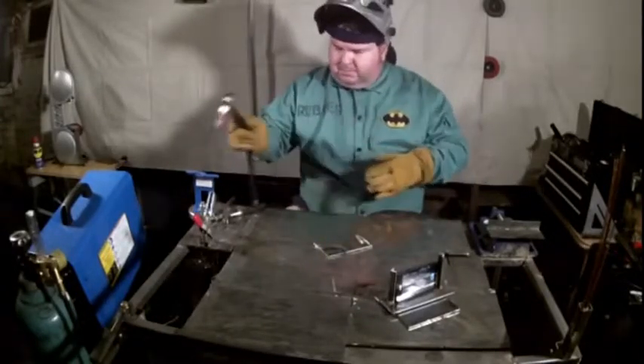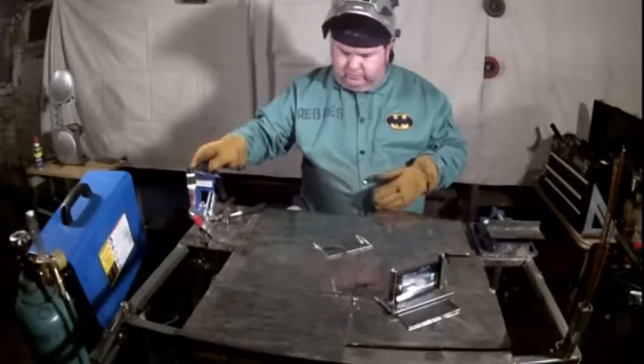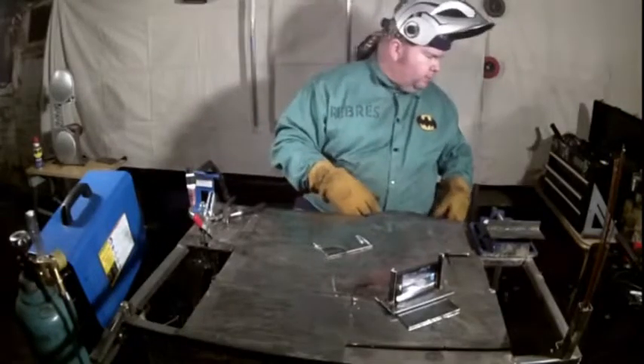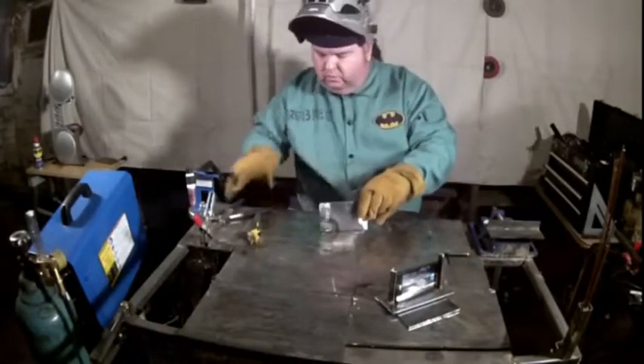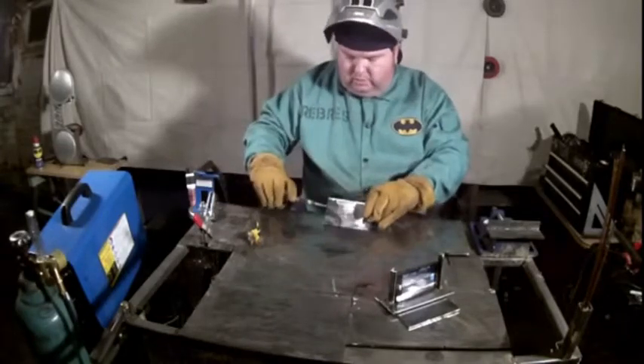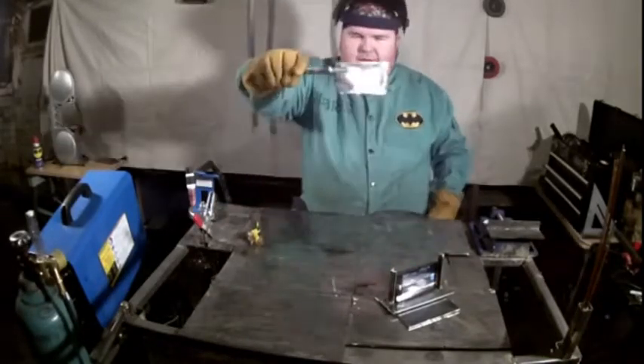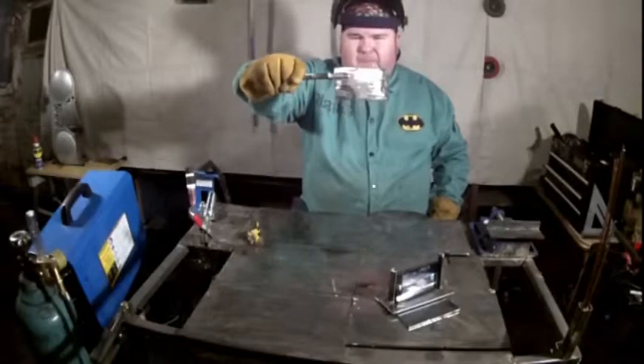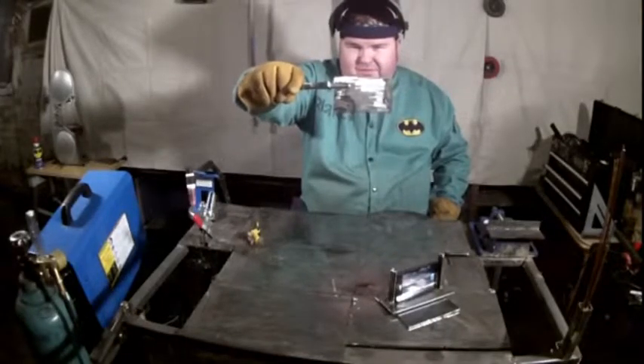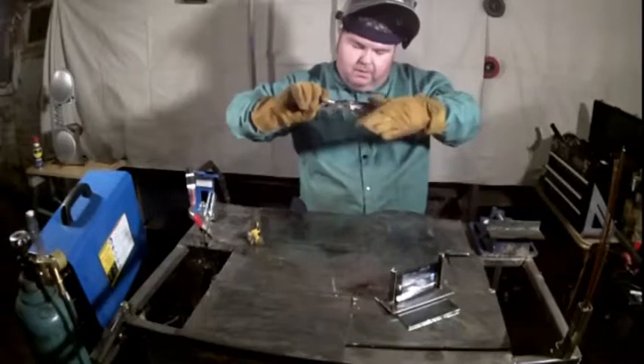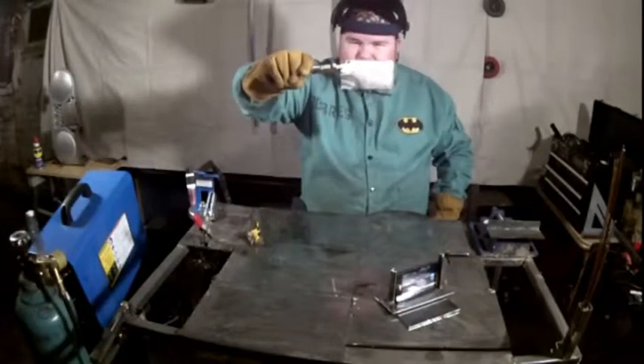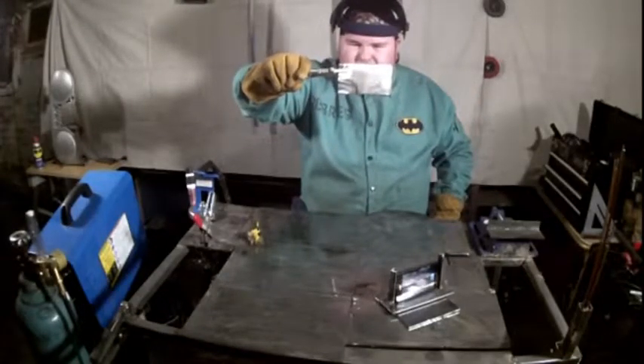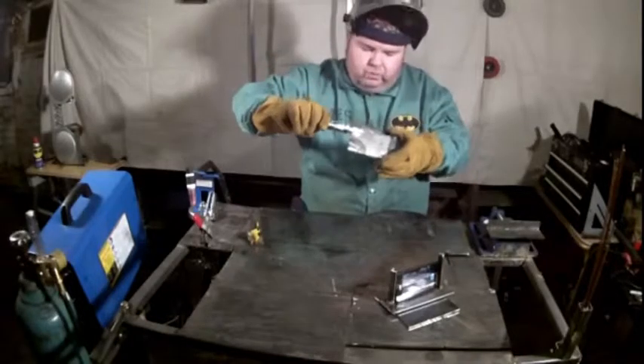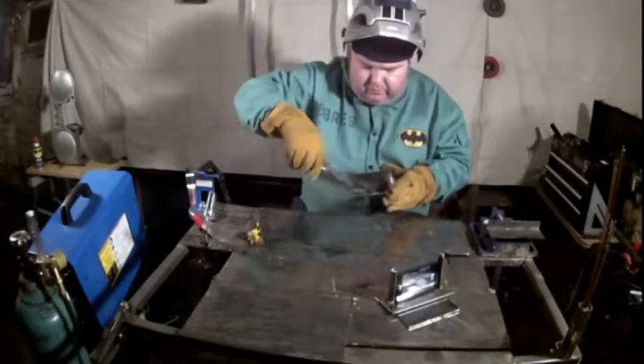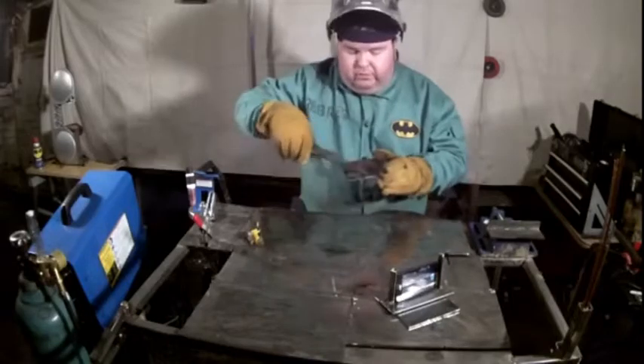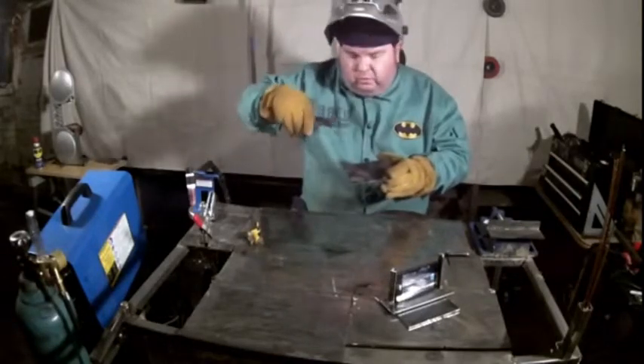Okay? Got 3, 2, 1. I know it's not straight, I didn't draw a line, but can you see that? It is smooth, the puddle size, the weld size is even. You can see the heat affected zone around it, and there's no crater at the end because I swirled and tapered off.